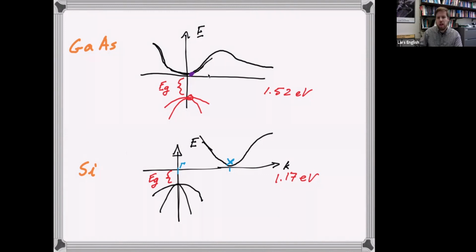What's interesting here is that the bottom of the conduction band is here at k equals 0, and the top of the valence band is also at k equals 0, and there is an energy difference of about 1.52 electron volts. So the E sub g, the gap energy here, is about 1.5 electron volts. But the valence band and the conduction band are facing each other in k space for gallium arsenide. But that is not the case for silicon.